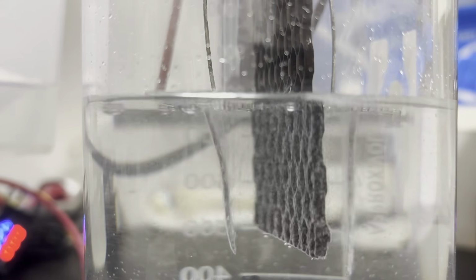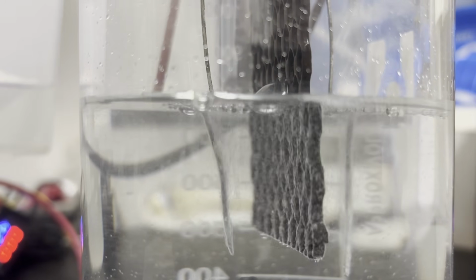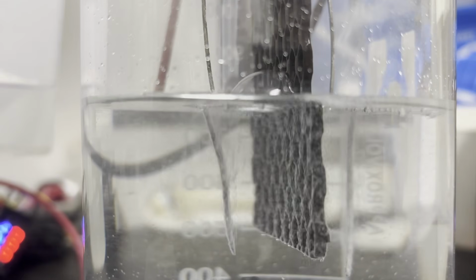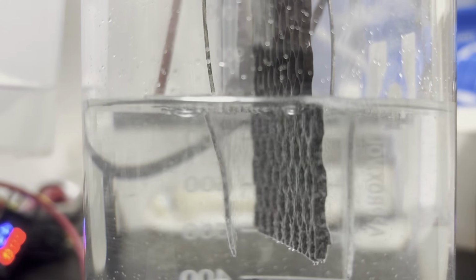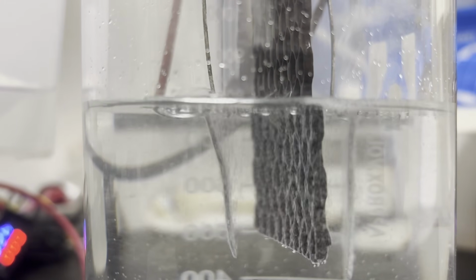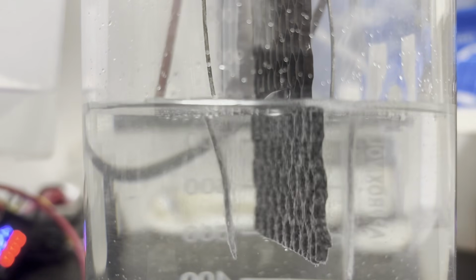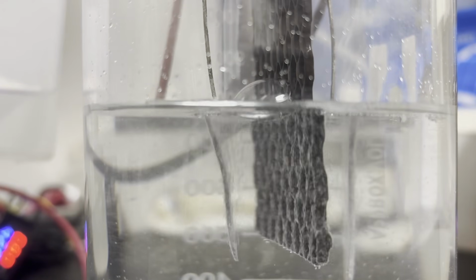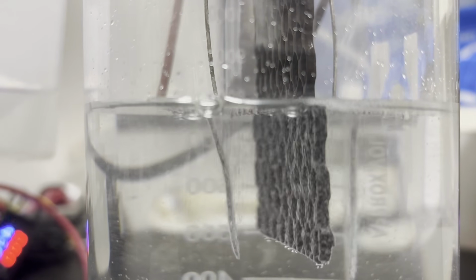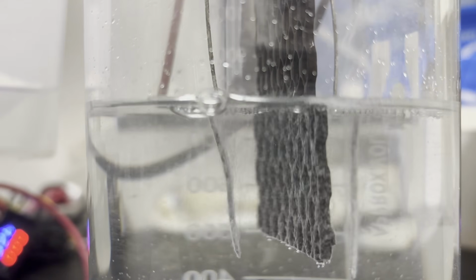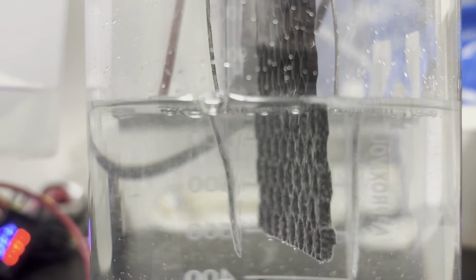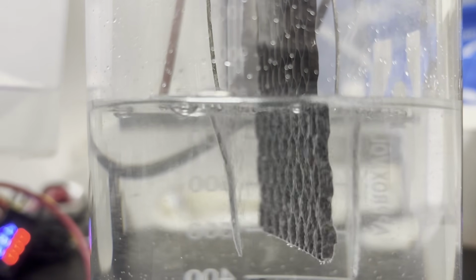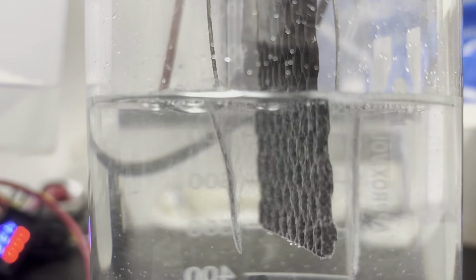It is obviously possible to make good lead dioxide electrodes myself, but I didn't choose to do that due to the toxicity of lead salts and the complexity of the procedure. In short, an antimony tin oxide layer needs to be coated onto titanium mesh substrate before depositing alpha lead dioxide in an alkaline bath and finally beta lead dioxide in an acidic bath. I might do it in the future, but for now I simply use an electrode made by someone else.